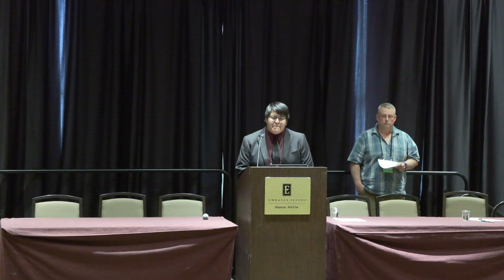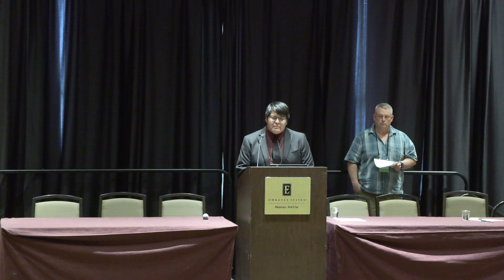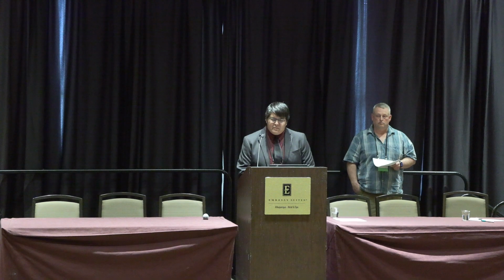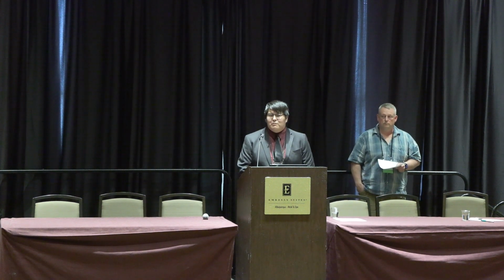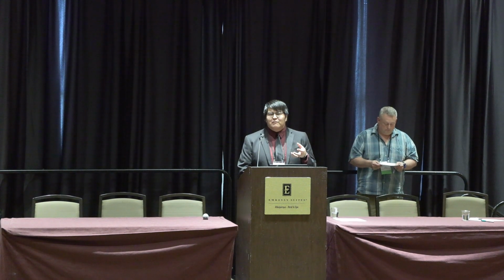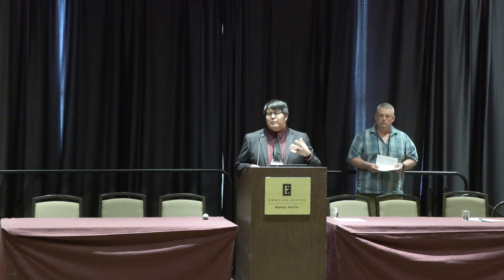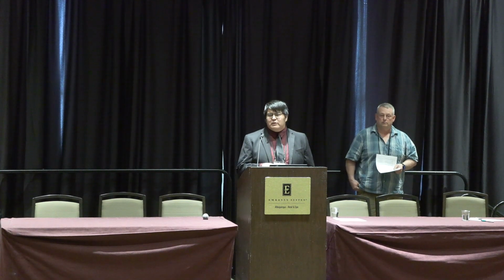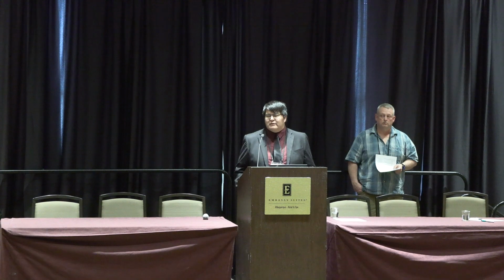You listed drying times. How long did it take to achieve a saturated condition? How long were you exposing the substrate to moisture prior to starting the clock? So we just maintain moisture. As we're mixing the UHPC, we're just constantly providing moisture on that surface and keeping it at that saturated condition.